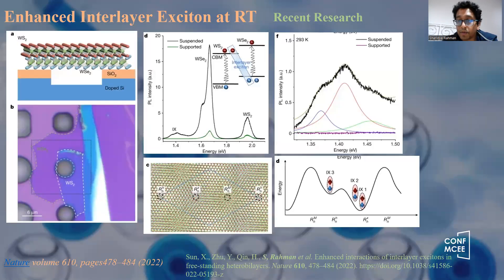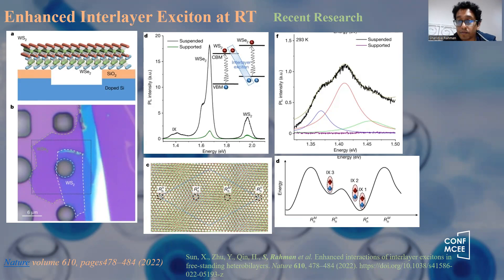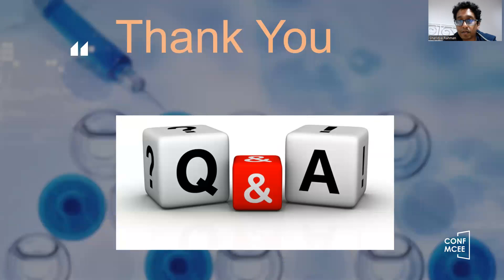Taking motivation from the literature, one of our recent works was published in Nature, combining a tungsten disulfide and tungsten diselenide heterostructure. We were able to reduce dielectric screening by etching the substrate, and as a result obtained interlayer excitons at room temperature, modulating them using temperature and other factors. Due to the three different regions of interest in the moiré superlattice, we were able to identify three different kinds of interlayer excitons at room temperature. This is why interlayer excitons and moiré heterostructures are a very exciting and rapidly growing area of research. Thank you everyone for listening.